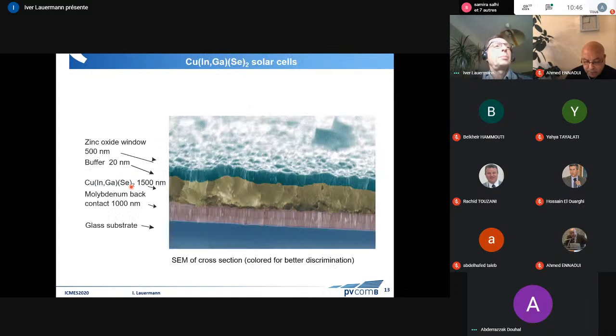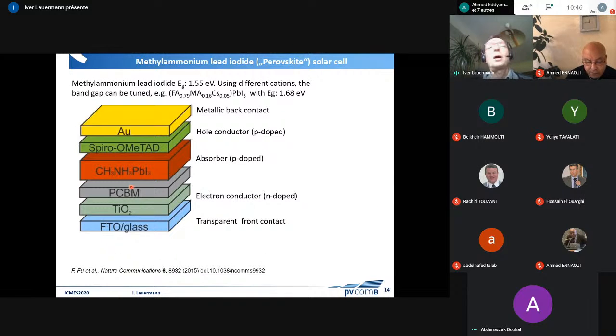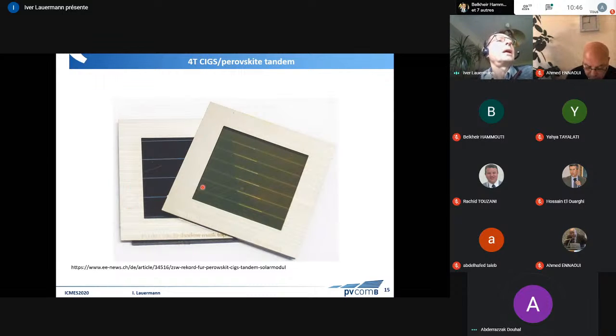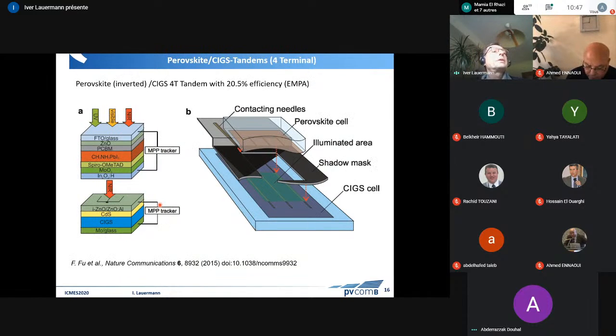So we've got the bottom cell, we've got a top cell, and now we aim to combine them to a tandem. Now, as I said, the simple way is a 4-terminal, and this has been shown by ZSW, for example. This is our semi-transparent top cell, the perovskite. It's actually a module. And here we have the bottom cell, the CIGS. This is not what we're doing at HZB. This is another example here where you see all these layers. Again, a bottom cell independent of a top cell with an efficiency of more than 20%. This was shown by EMPA already in 2015.